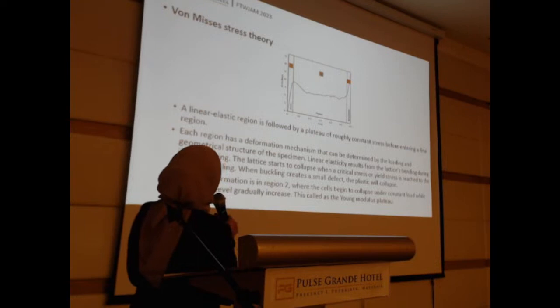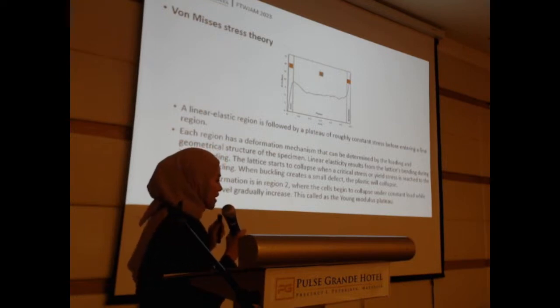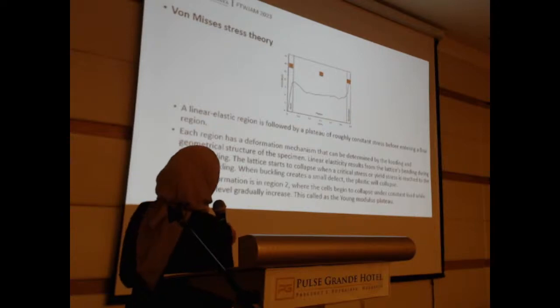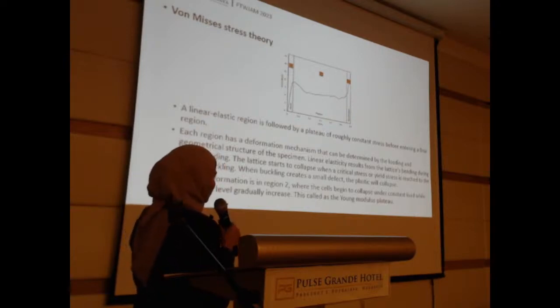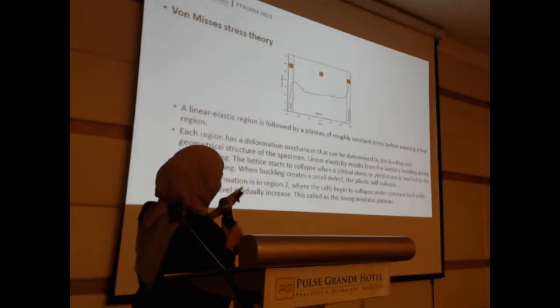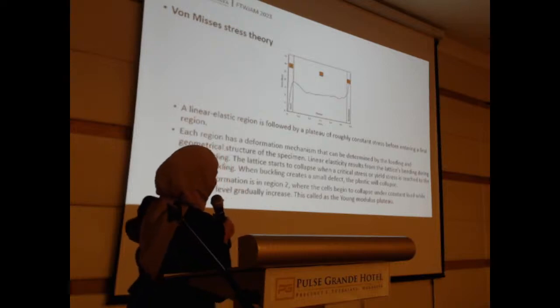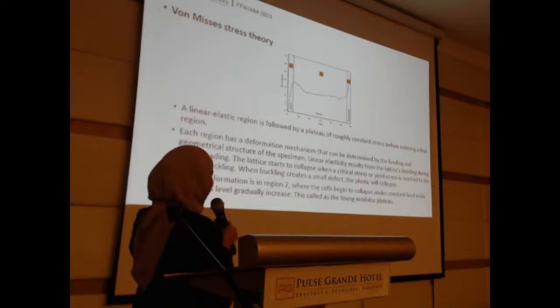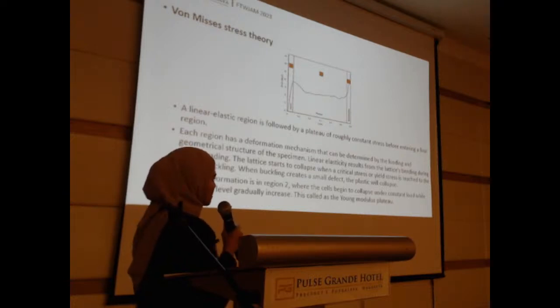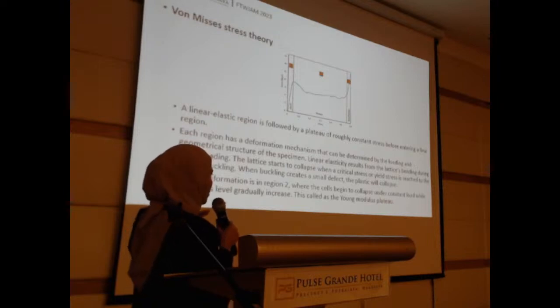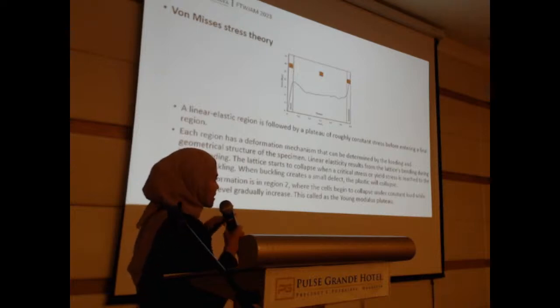Von-Mises stress theory is related to the compression behavior. A linear elastic region is followed by a plateau of roughly constant stress before entering the final region, which is densification. Each region has a deformation mechanism that is determined by the loading and the geometrical structure of the specimen. Linear elasticity results from the lattice bending during initial loading. The cells of the lattice start to collapse when the critical stress or yield stress is reached at elastic buckling.